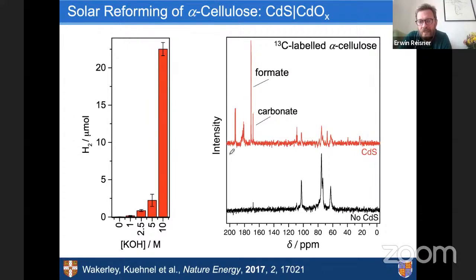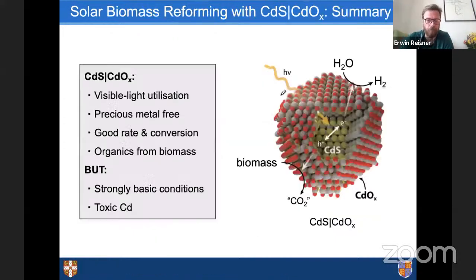our first system that indeed from the C13 NMR we not only formed carbonate, of course the CO2 would be trapped as carbonate under this pH system, but also formate. So this in principle already showed the possibility to accumulate interesting organic molecules. Maybe not the most exciting one, but formate is still an interesting energy carrier. There's development of even formic acid fuel cells. And so we were quite excited just to actually be able to detect significant amounts. And it was even the major product in the system.